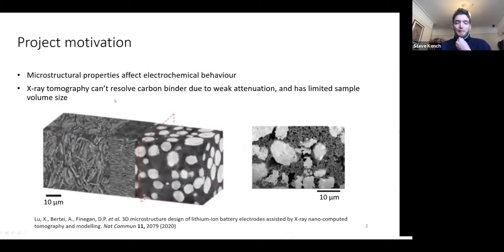So, the structural arrangement of these different phases really strongly influences the actual performance of our battery. For example, the more porous our material is, the easier it is for that lithium to penetrate into the cathode and therefore the faster we can discharge and that means higher rates of power. But conversely, the more porous we are, the less active material we have and the lower capacity our battery is going to have. So, there's some really complicated interplay between different microstructural properties of cathodes that we want to try and understand so that we can optimize that performance for a particular use case. My project specifically has been about looking at how we can go from single 2D images and generate 3D volumes.